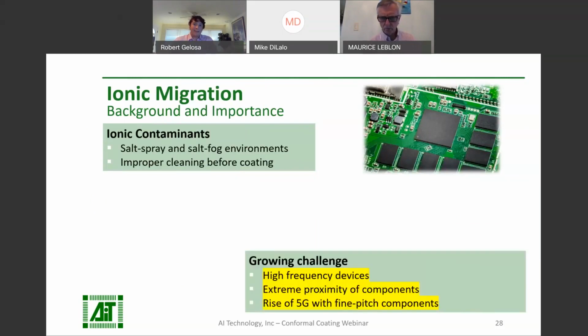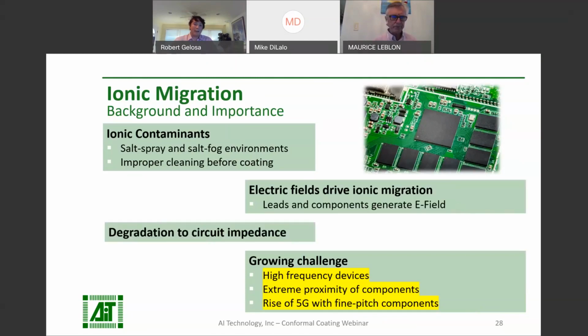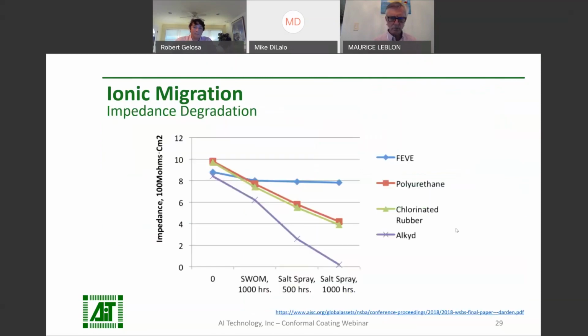As technology advances, there's a drive for everything to be higher and higher frequency and smaller, thinner, and more tightly packed. But the higher frequency of our devices and the closer the leads and components are in proximity to each other, the stronger the electric field that drives the movement of ions through conformal coatings. This can lead to a drop in resistivity of the coatings and even lead to short circuits. Advanced weather aging tests and salt spray testing can be used to determine how well different polymers prevent ionic migration.